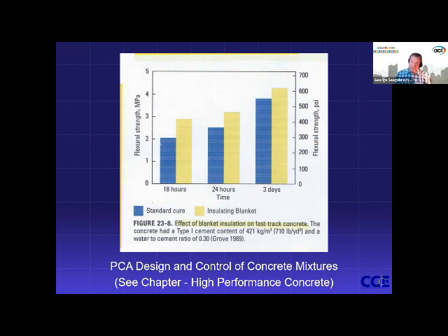I'm just noticing, and this is just me, I didn't bring this whole chapter onto one slide, obviously. The first 18 hours has the highest bump, probably because it's encapsulating some of the heat of hydration from such a rich mix early on. And again, that's a great way to use what concrete's given you, the heat of hydration, and, you know, temperature, moisture, time. That temperature all comes from the heat of hydration as well. So encapsulate it, use it. Don't let it just drift off into the air. And then that diminishes as you go to later ages.